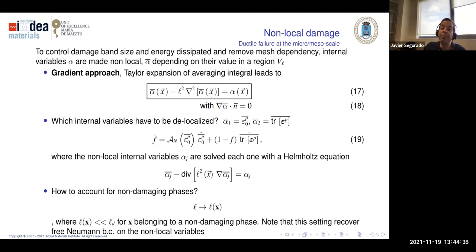size dependent. But if L is a physical length related to the distance between nanoporosity and things like that, then what we are getting is that the deformation now localizes in bands, and the bands will be of size L. So we are not anymore depending on the element or voxel size. We are depending on a physical parameter that is this L.